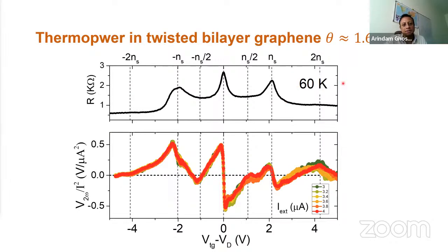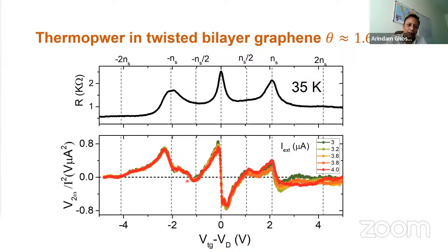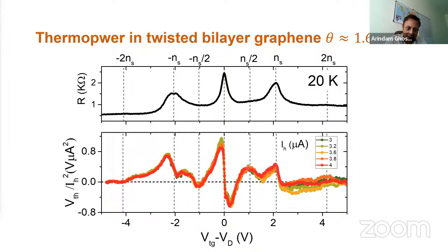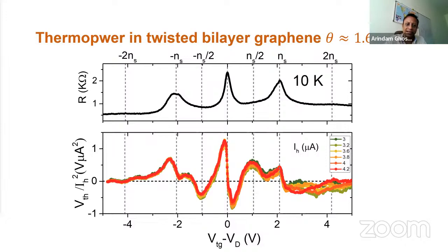So now I start cooling the system to less than 60 degrees, to 35 Kelvin. You can see there's a small additional component which cannot be explained by the semi-classical model starts to emerge. You can decrease it to 20 Kelvin. You can clearly see now there is an additional peak over here, an additional dip here that says that your thermopower cannot be explained by a simple derivative of the resistance with respect to density. This goes further, and you can see at 10 Kelvin, there's a very strong dip, and there's a very strong peak at minus and plus n_s, which clearly shows that the Boltzmann semi-classical model is failing, and we are no longer having a simple diffusive metal in our system.